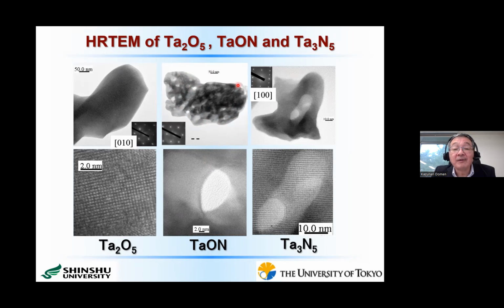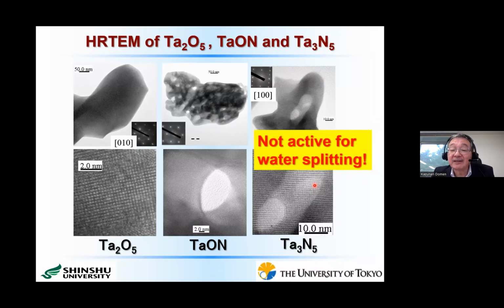However, when we took the electron diffraction pattern from these porous particles, we still observe a sharp spot like this one. So this particle is actually a porous single crystalline particle. And even in the case of Ta3N5, from this particle, we again obtained this kind of sharp spot. So we consider that we are preparing considerably good quality particles. That's why we had been working on this type of materials for more than 15 years. However, as I said, we have never succeeded in the overall water splitting reaction.